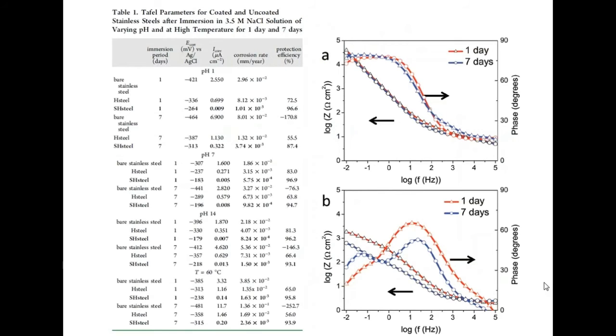Another is by EIS, electrochemical impedance spectroscopy. Both the Bode plot and Nyquist plot show a good stability of the film even after 7 days, and that the non-wetting behavior produces an efficiency all the way to 96%. In other words, these are robust films that have very little diffusion or transport of corrosion to the other side of the steel.